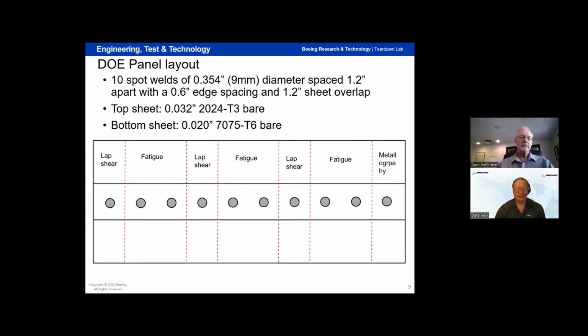Go ahead, Dave. And those sizes that Scott mentioned, the edge distance being 2 times the diameter and the rivet spacing being 4 times the diameter, those are typical values for aerospace assemblies. An edge distance of twice the diameter gives you the best fastener bearing stress allowables. That really is not the case here because there's actually not a hole. You're not pushing hole to hole, you're pushing solid material to solid material. So it's actually a better joint. But again, there's standards that everybody wants to see, and we thought we'd start with the aircraft standards. So next slide. Yep.